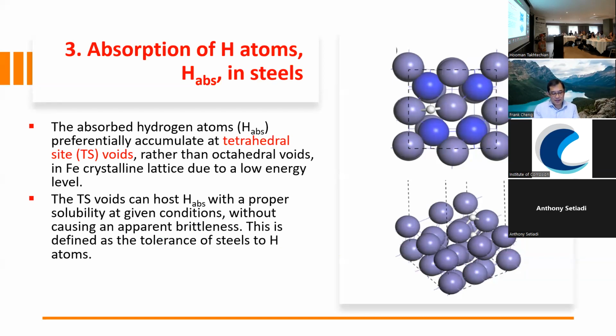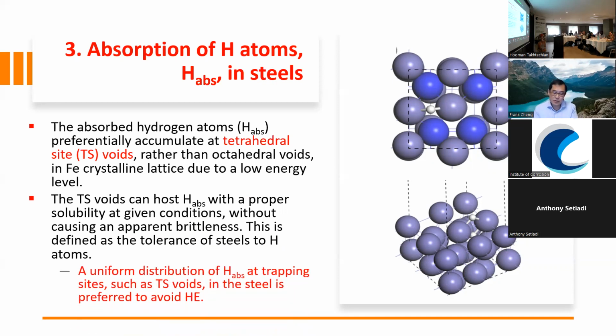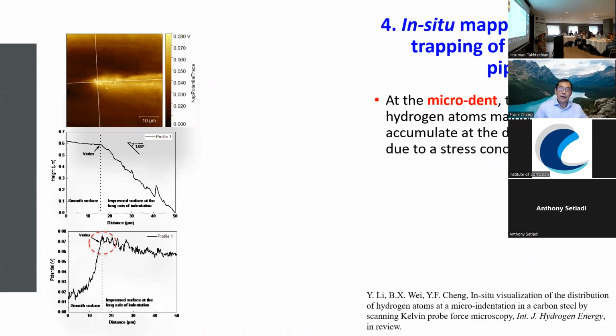So that also means the certain steel has a certain tolerance to the hydrogen atom. Okay, not a single hydrogen atom can cause a cracking problem. No, there is a certain tolerance to hydrogen atom accumulation. And so uniform distribution of hydrogen is not a big trouble to the steel. And as we introduced in the fundamental part, what we worry about is the local trapping of hydrogen. So that's a local accumulation of hydrogen atoms to reach a certain concentration.